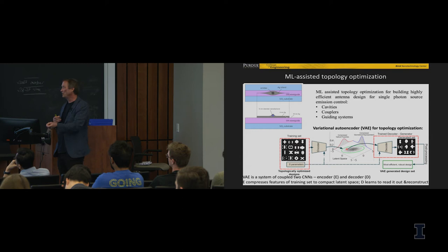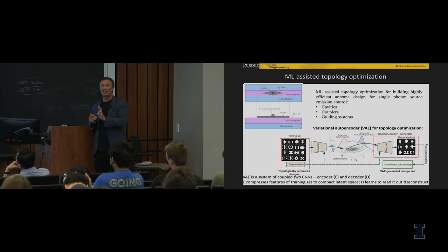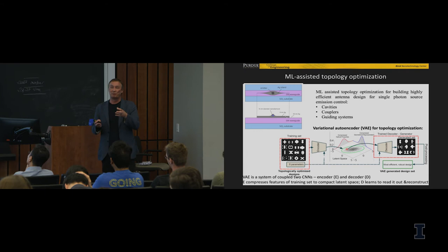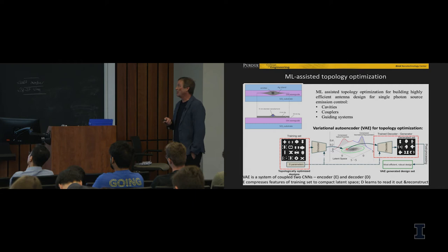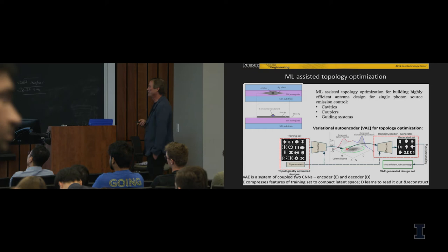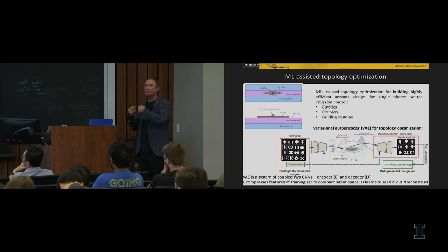I pointed out how critical it is to have the right antenna, which would be able to outcouple emission rates faster than the decoherence rate. And we use a simple cube. Clearly, it's not the best possible design. So, to optimize other systems like cavities, couplers, or antennas, we use yet another machine learning approach. It's called a variational autoencoder, to basically optimize all the structures. And I should emphasize it goes beyond conventional inverse design, beyond topology optimization. With topology optimization, you start from some random point and probably would end up in some local maximum. To get to the global maximum, actually you have to do this machine learning assisted topology optimization. We use actually a topology optimized design as a training set, as a starting point.